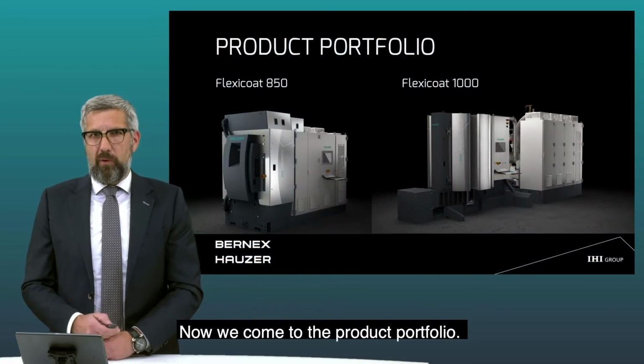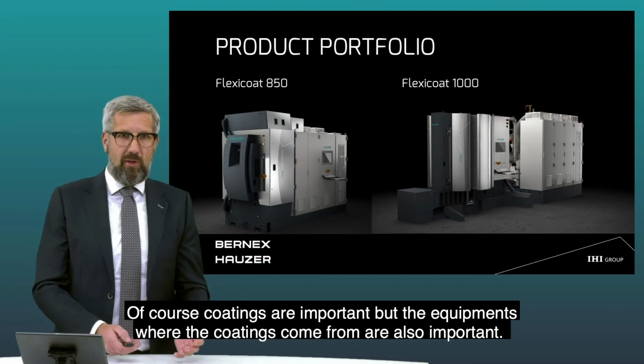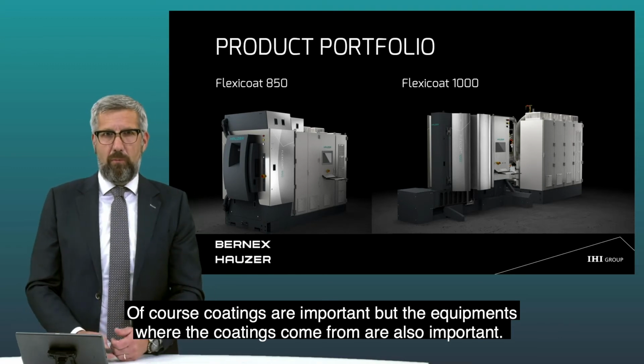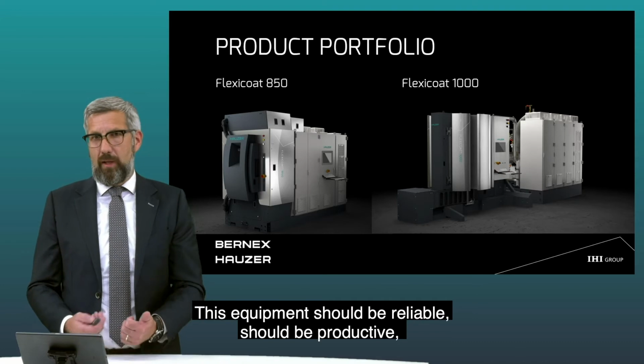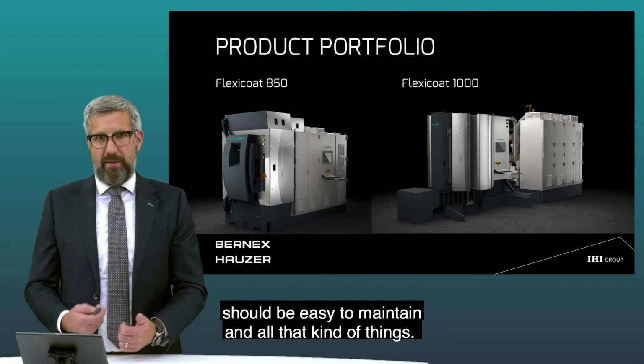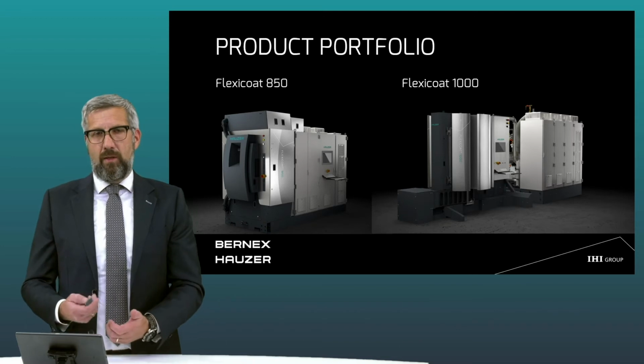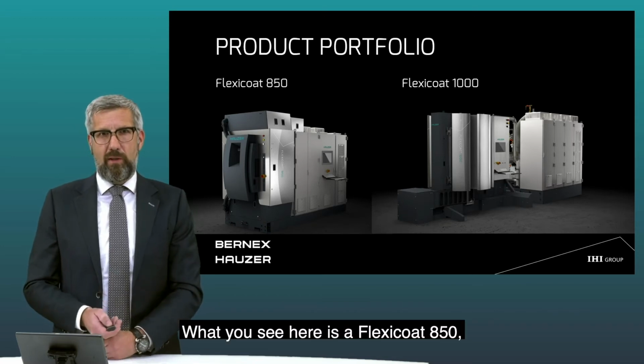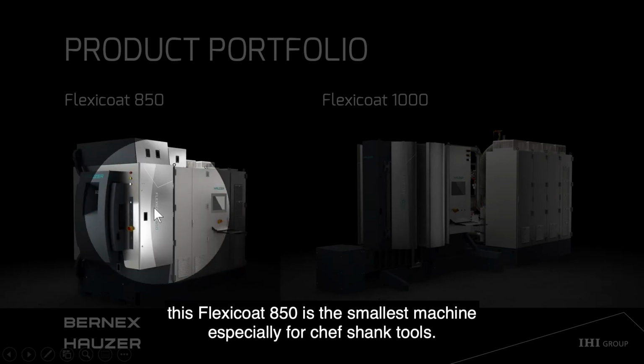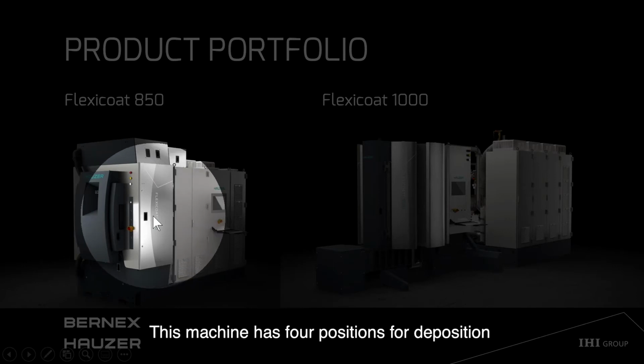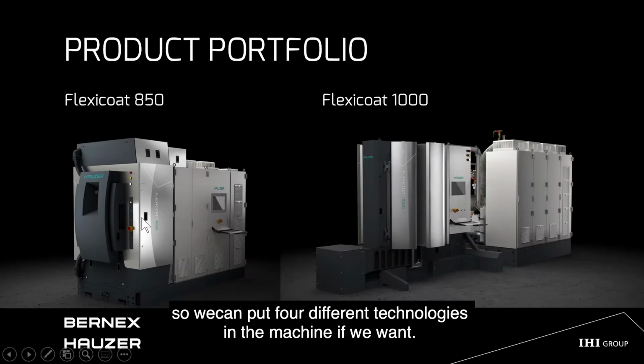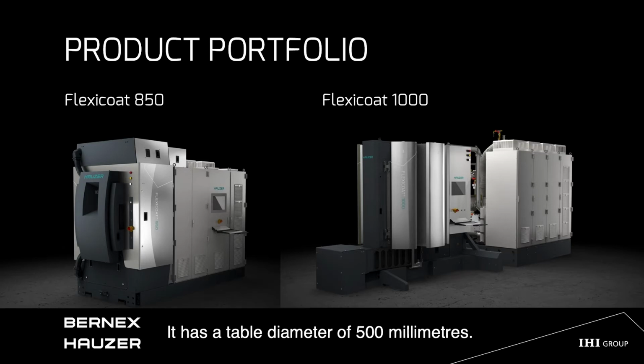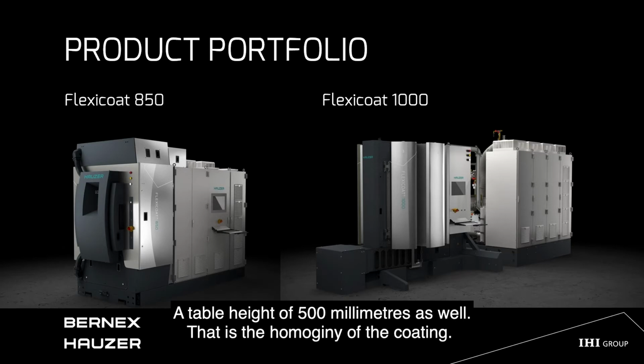So then we come to the product portfolio. So of course, coatings are important, but the equipment where the coatings come from are also important. This equipment should be reliable, should be productive, should be easy to maintain, and all kind of things. What you see here is a FlexCoat 850. This FlexCoat 850 is the smallest machine, especially for shank tools. This machine has 4 flanges, so we can put in 4 different technologies if we want. It has a table diameter of 500 millimeter, a table height of 500 millimeter as well. That is the homogeneous zone of the coating.